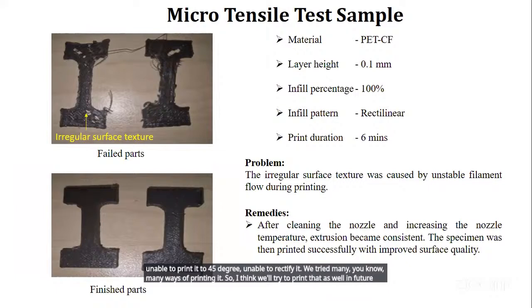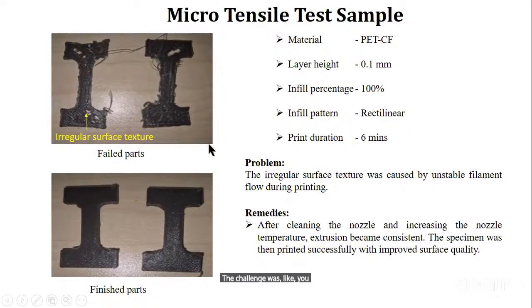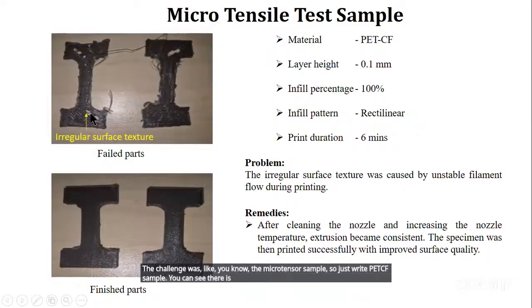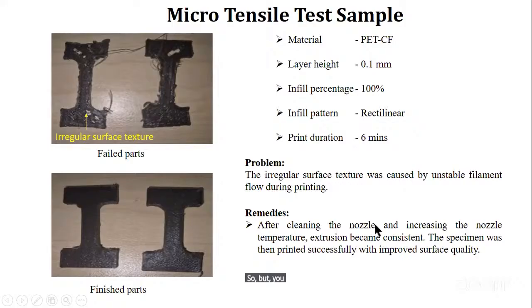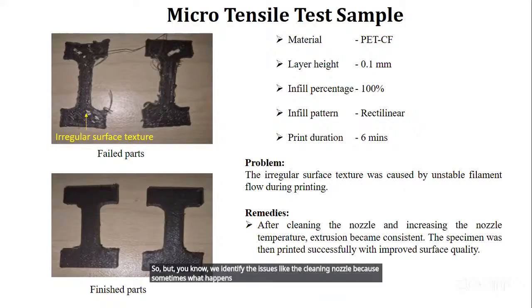Another challenge was the micro tensile sample. We tried a PETCF sample. You can see there is some irregular surface texture on the micro tensile sample when trying to print the PETCF. It was taking just 6 minutes, but we were not getting a good micro tensile sample. But we identified the issue: cleaning the nozzle, because sometimes when you change to different materials, there will be some debris of particles inside the nozzle, right?